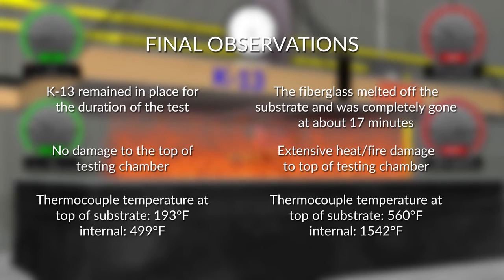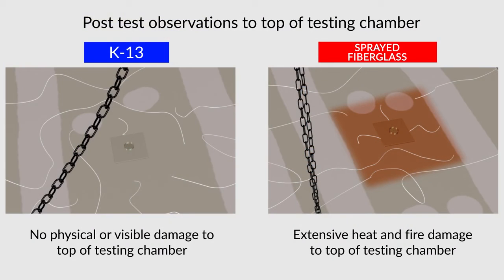The fiberglass melted off the substrate and was completely gone at 17 minutes. Extensive heat, fire damage to top of testing chamber. Thermocouple temperature at top of substrate, 560 Fahrenheit, internal 1,542 Fahrenheit. Post-test observation to top of testing chamber. K-13, no physical or visible damage. Sprayed fiberglass, extensive heat and fire damage.